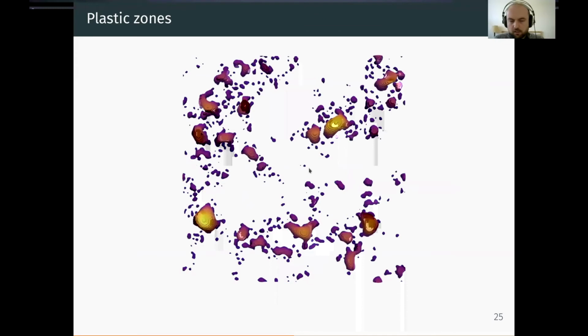So that's the end of the technical part. This is one of the results that we can get from such a simulation. These are the plastic zones. So those are all the zones where we have plastic deformation in a rough surface contact. The color here indicates the depth. So you can see most of those plastic zones actually located close to the surface.